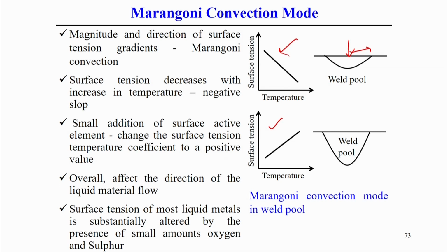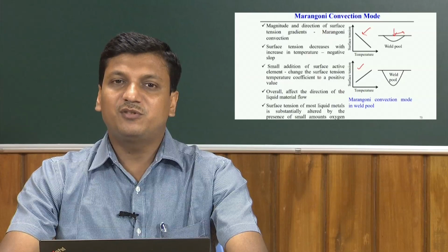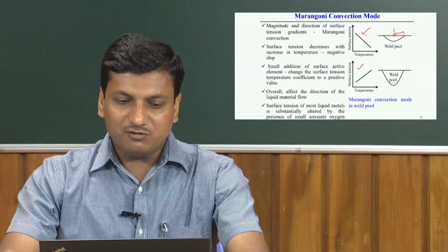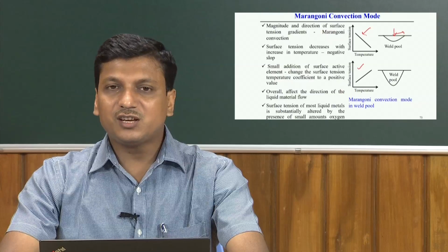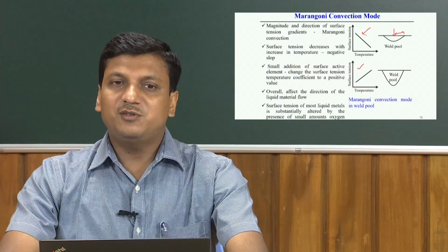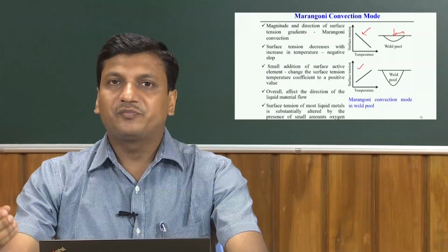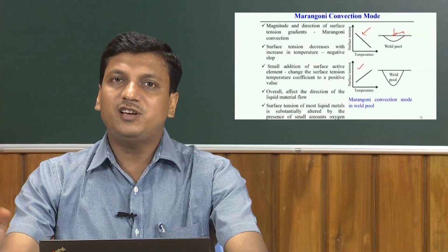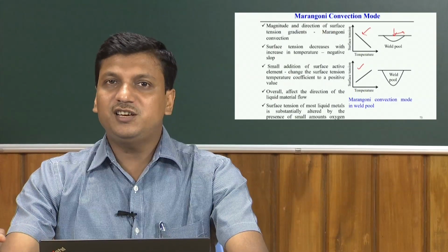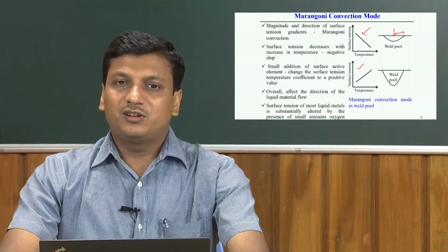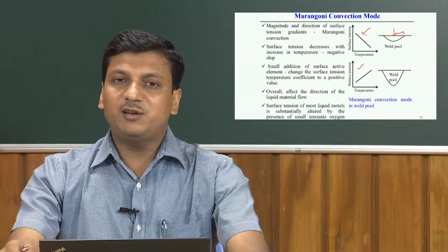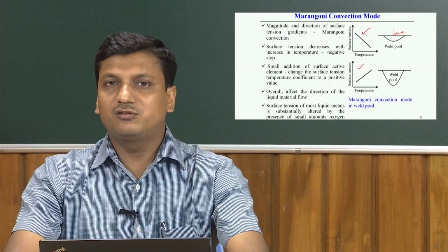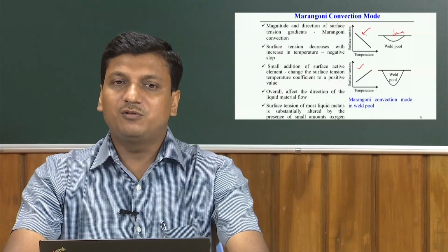But of course, the quantity, the amount or concentration of the surface active elements also plays a role. Not just any amount of surface active elements can change this surface tension gradient from negative to positive. So, what we understand from here is that the presence of surface active elements affects the direction of the material flow, and that influences the change of the weld pool size and shape. These are the two types of Marangoni convection mode that we probably observe in the weld pool.